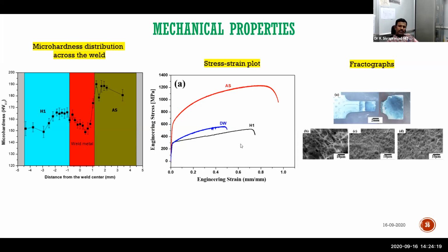And it could not project 80% or 90% ductility because, as I told you, an unmixed zone formed at the fusion boundary, and in that location only it has failed. That unmixed zone where a small amount of BCC has formed, there only it has failed. So the reason for failure is that undesirable phase formed. Had it been that in the unmixed zone the undesirable BCC phase could not have formed, and there also single phase FCC formed, probably we could have got our curve still much higher, like this.